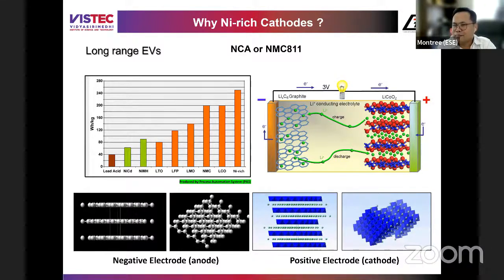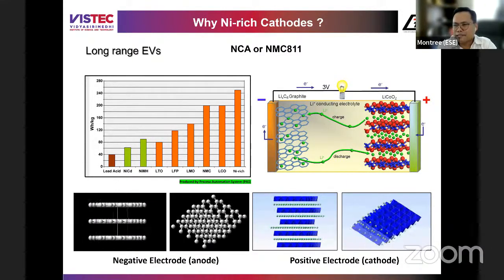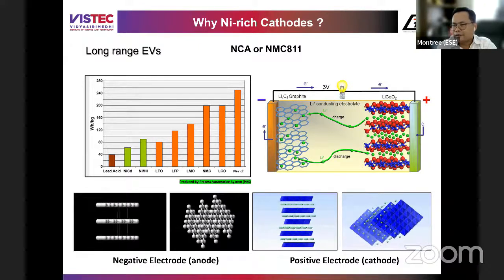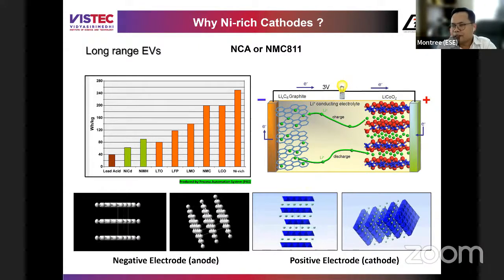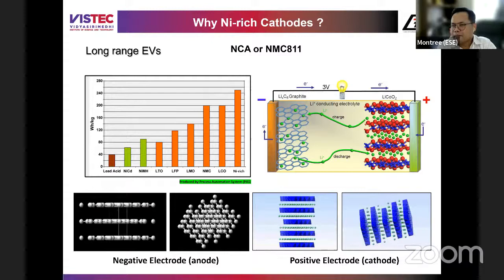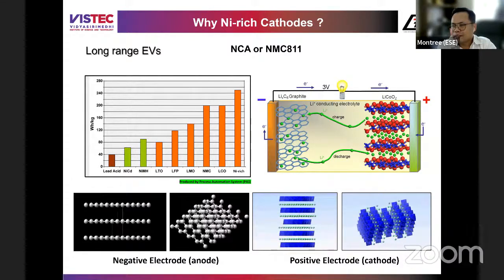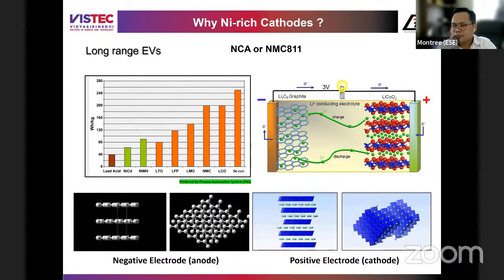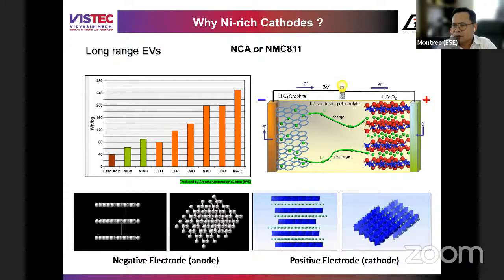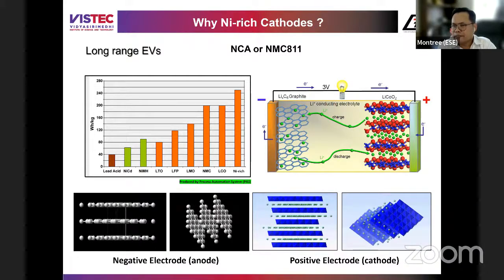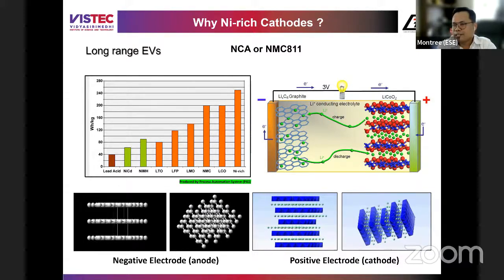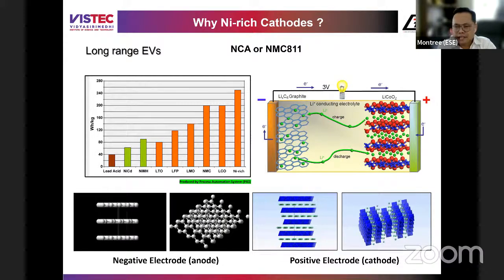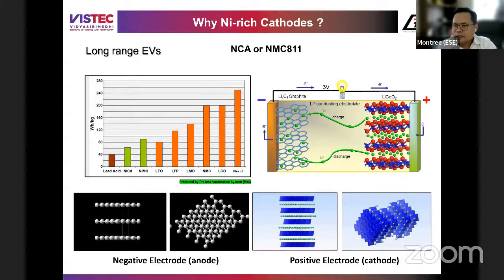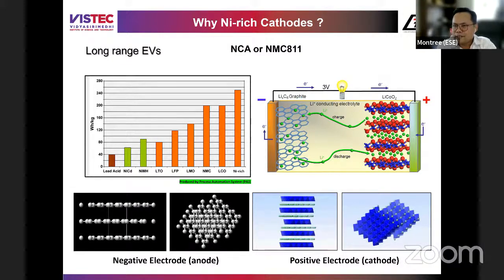We don't like lithium metal, because it can seed particles and form lithium dendrites, growing in one dimension, right? It is very dangerous for lithium metal dendrites to grow and make contact between anode and cathode, because of short circuit and thermal runaway. This is the safety concern mechanism of lithium dendrite.